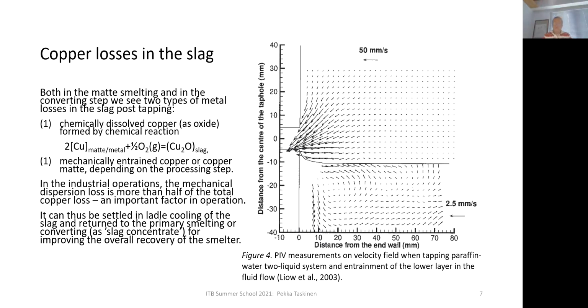The other form, which is often much more in terms of copper concentration in copper making, is the mechanically entrained copper or copper matte, which can be due to unsettled droplets, fine droplets of metal or matte, which, for certain reasons, don't have time to settle, or they are due to kind of too hasty operation of slag tapping.